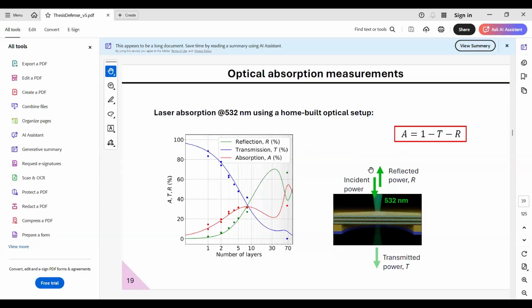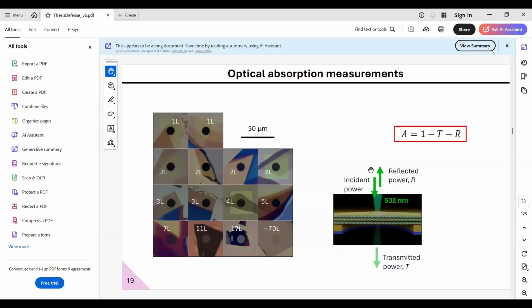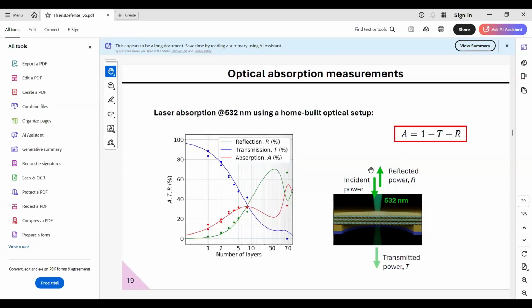So it's around 15% for the monolayer, the absorption. One is like 9% and the other is 15 or a bit less. These are two different samples, the two I showed here. They give slightly different values of absorption, but the reflection is basically the same. It's the transmission that changes a bit. It could be that placing the samples or the control substrate used for the correction introduces a bit of error, or that the samples have slightly different doping, whatever, that would lead to slightly different values.